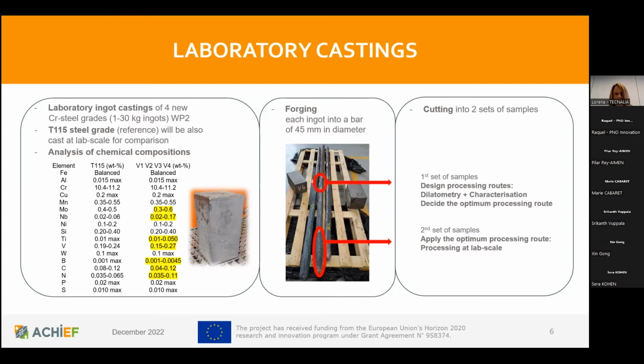We take a first set of samples from these 4 bars to accomplish the dilatometry study, in which we design and apply different processing routes to different steel grades to see the effects. So we characterize then the samples, and based on the results obtained, we decide the optimum processing route for each steel grade. And then these optimum processing routes are applied at lab scale on the steel grades, but using the same material of higher dimensions. This is why we call it a lab scale activity.